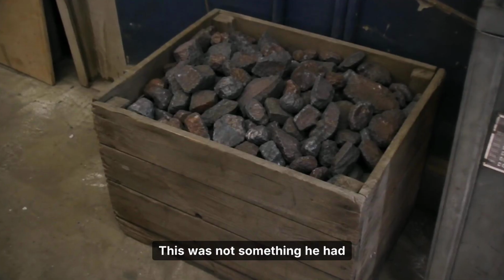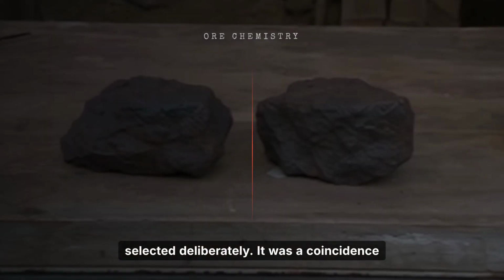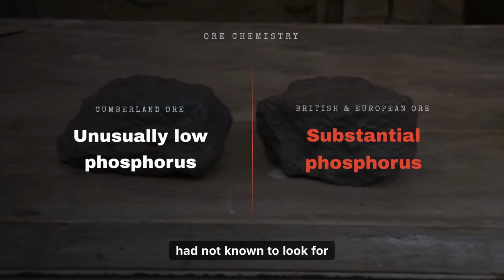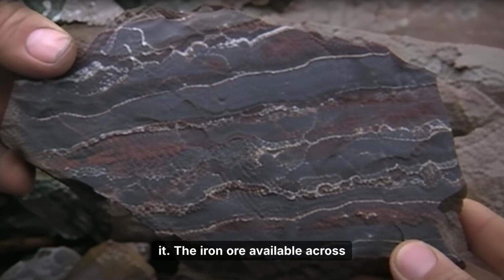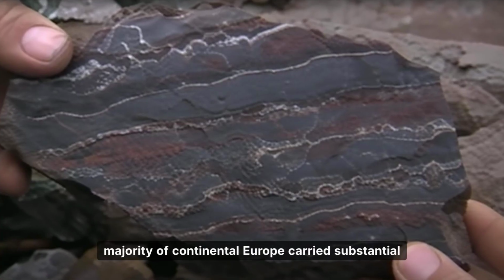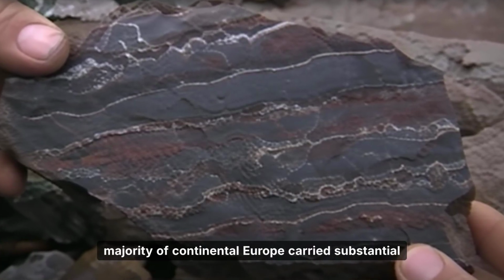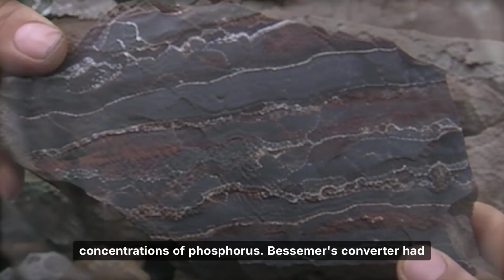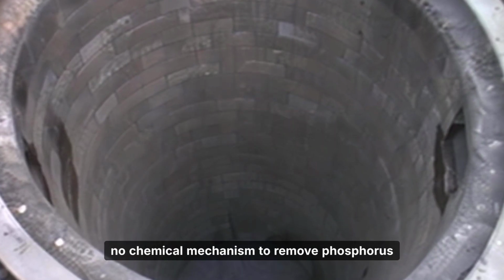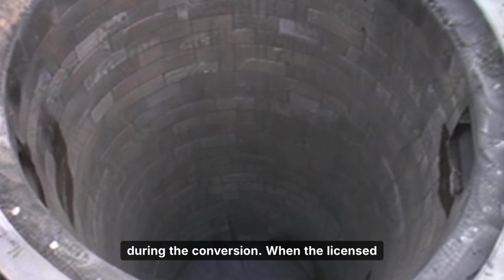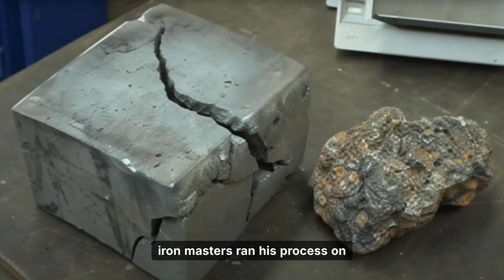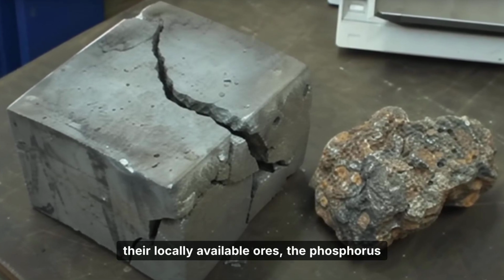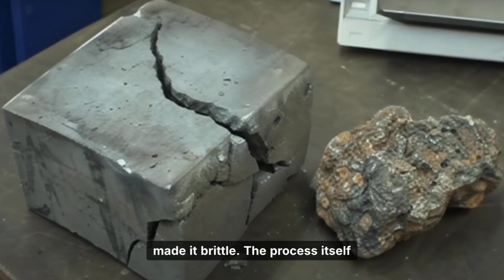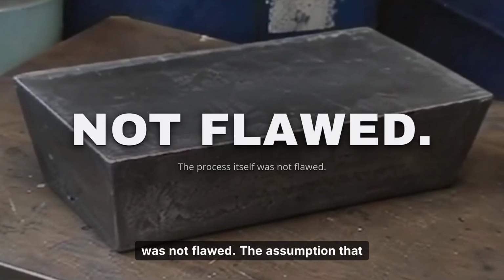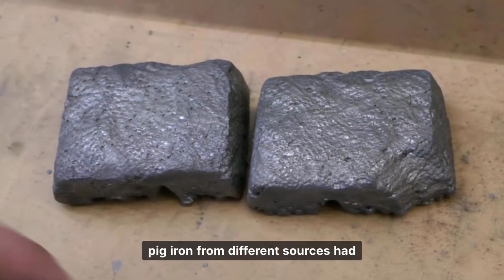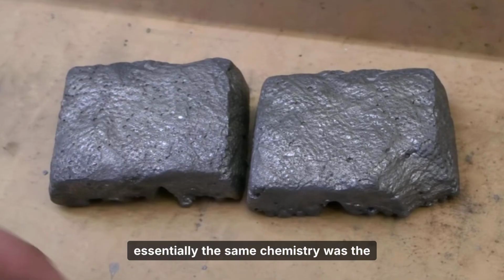This was not something he had selected deliberately. It was a coincidence he had not identified because he had not known to look for it. The iron ore available across most of Britain and throughout the majority of continental Europe carried substantial concentrations of phosphorus. Bessemer's converter had no chemical mechanism to remove phosphorus during the conversion. When the licensed iron masters ran his process on their locally available ores, the phosphorus remained in the finished steel and made it brittle. The process itself was not flawed. The assumption that pig iron from different sources had essentially the same chemistry was the problem.